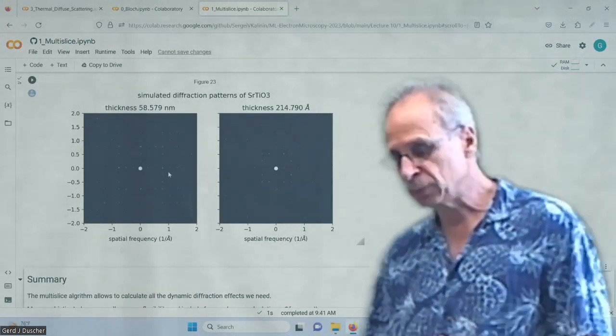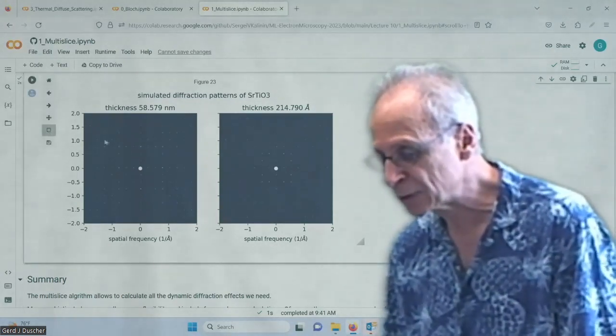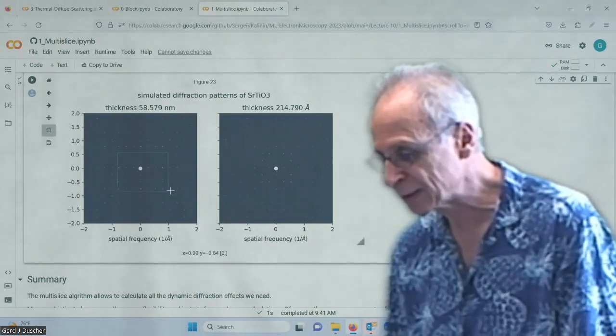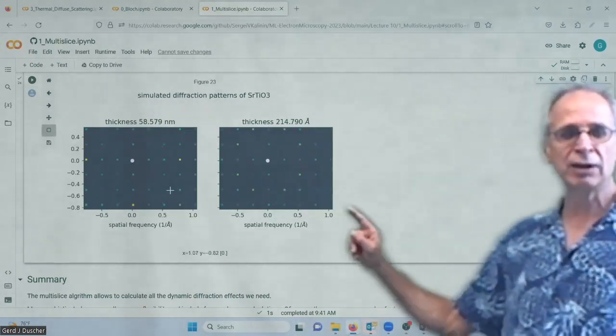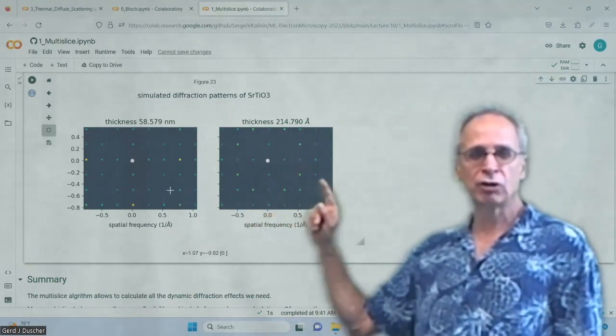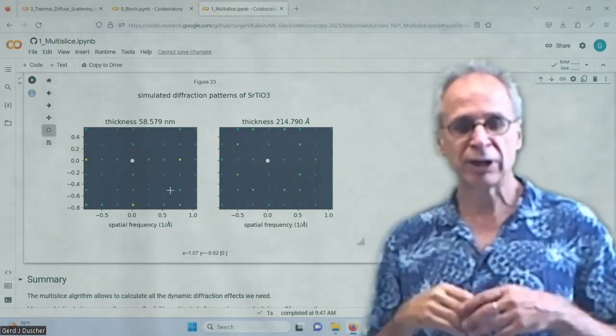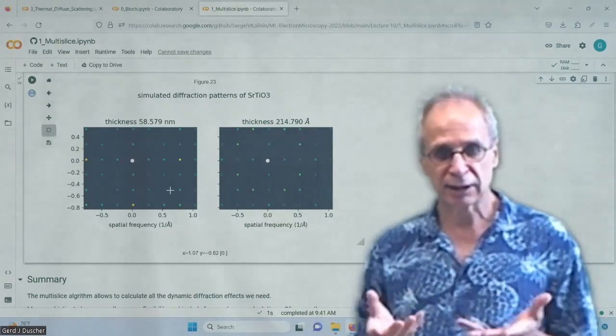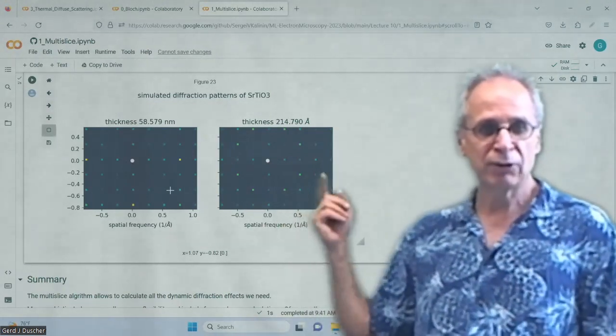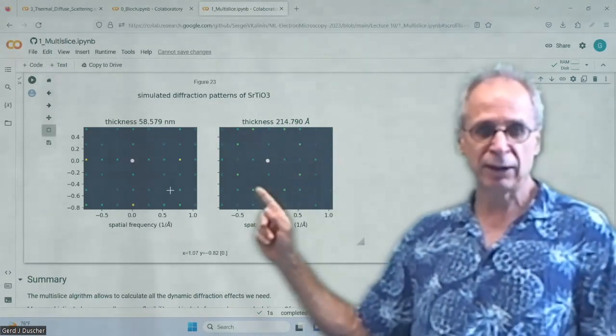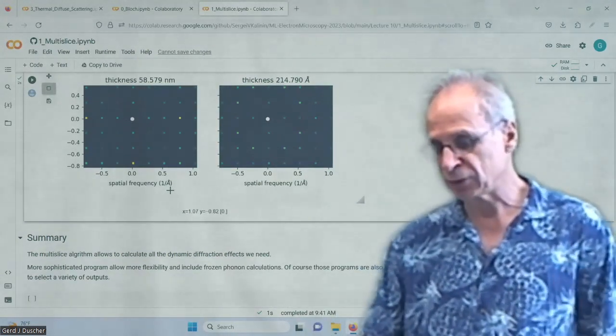We get the diffraction patterns. Zooming in a little bit for better intensities — you can see the Bragg peaks have changed intensities. They did not change their kinematically-determined angle, but they interact and we have changes depending on thickness. This is the multi-slice algorithm — there's not really that much mathematics to it because you've changed it into an iterative process. Let's go and do the same thing for the convergent beam electron diffraction.